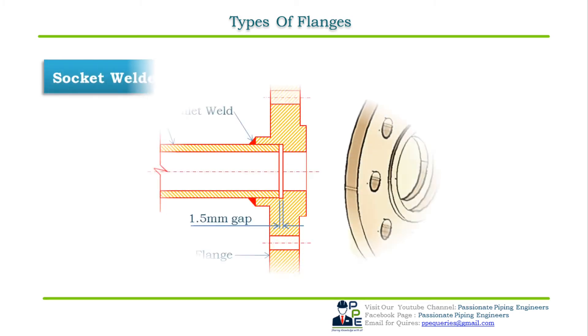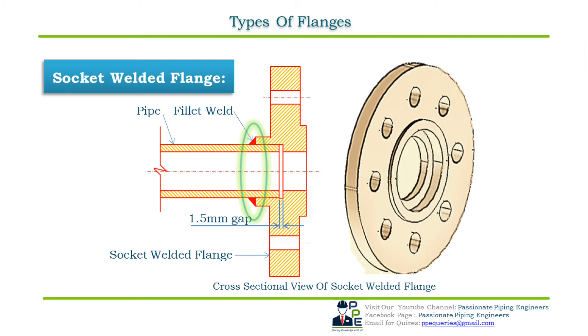The third type is the socket welded flange. Socket welded flanges are connected to the pipe using a single fillet weld executed on the outer side of the flange, according to ASME B31.3. The pipe is first inserted into the socket of the flange until it reaches the bottom, then lifted by 1.5 mm, and finally fillet welded. Remember: only plain-end pipes can be used with socket welded flanges and fittings.